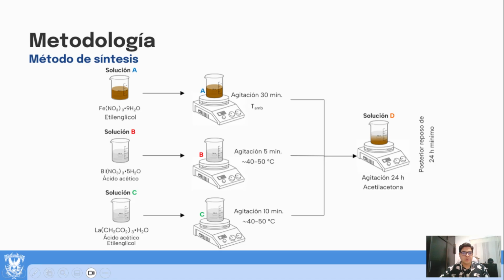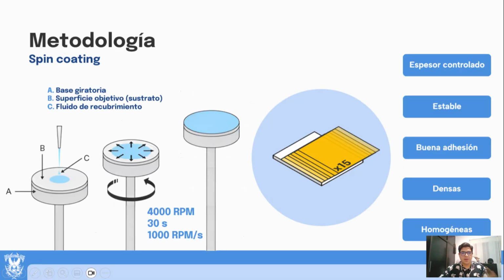To enhance sol stability, chelating agent acetylacetone is added, forming complexes with metal ions and retarding hydrolysis. The resulting solution undergoes continuous magnetic stirring for 24 hours at room temperature to ensure homogeneous mixing. Film deposition is performed via spin coating, a technique allowing precise control over film thickness through substrate rotation speed.